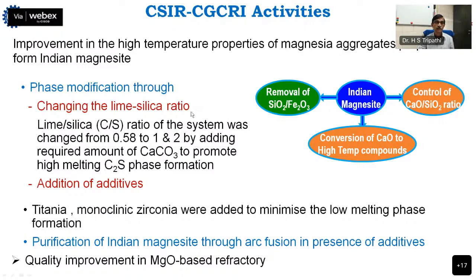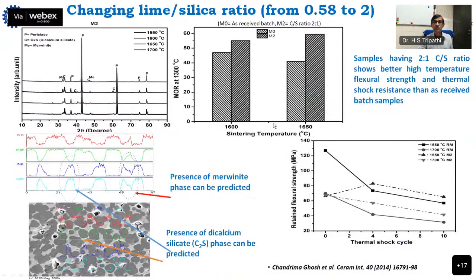So one approach is phase modification by changing the lime silica ratio. Originally, we selected some magnesite having a lime silica ratio of 0.58. We changed it to 1 and 2 by adjusting with some amount of calcium carbonate and so on. And in some cases, for major phase modification, we use some titania and monoclinic zirconia to form different phases, to consume the small amount of iron and calcium oxide present in the lime. And then finally, the purification of magnesite through arc fusion, so that we can remove both the silica and iron oxide.